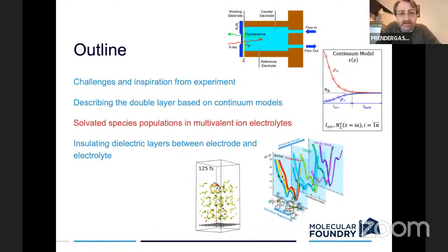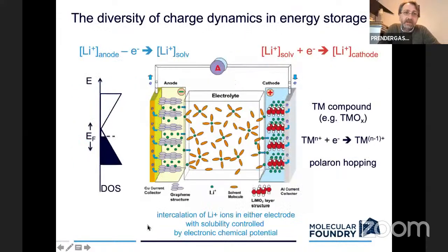Okay, so let's talk now about the solvated species that might exist inside our electrolyte. And we'll focus on multivalent ions here, like magnesium. So you might have seen this cartoon already. This is the rocking chair model, so-called by Michel Armand, for the lithium-ion battery, where you're basically moving lithium ions from one intercalation compound to another as you connect the external circuit and allow electrons to flow or to push them backwards with an external power source. So at the anode, you're creating solvated electrons, you're lowering the Fermi level of the system to do that. And then over on the cathode side, cathodes are typically maybe not electronically conducting in the traditional sense, in the ballistic sense. And instead what you see is changes in oxidation states of the transition metal atoms in this framework and hopping of electrons through those transition metals out to meet the ions and to neutralize them as they come in. Okay.